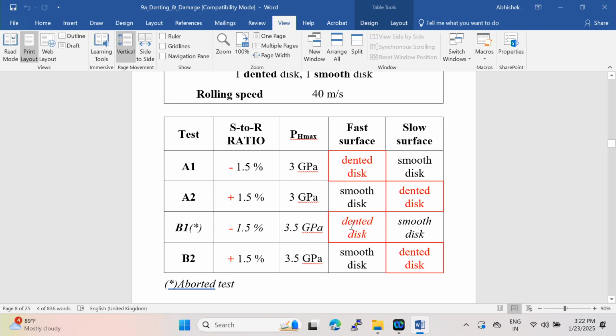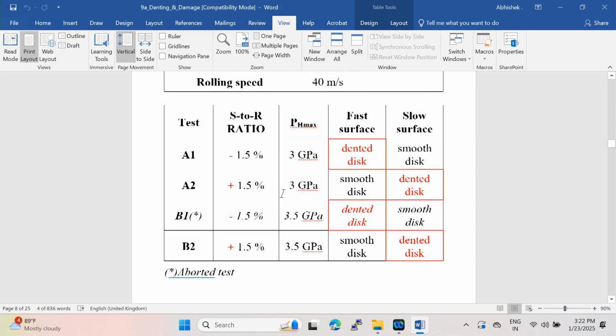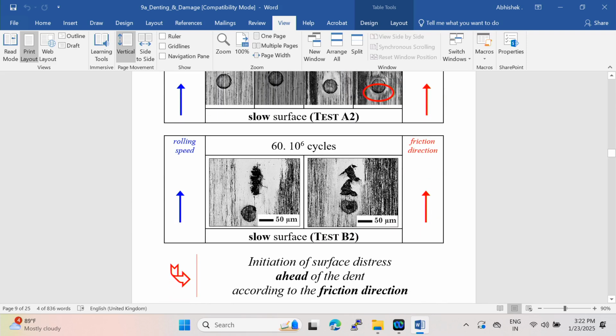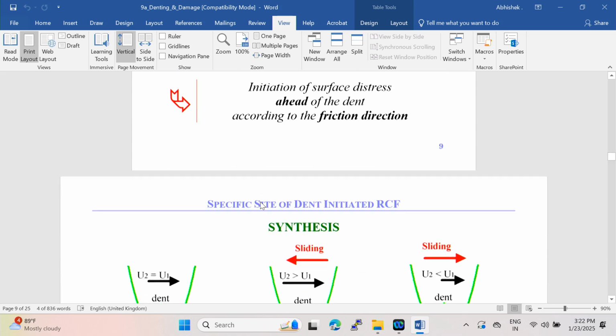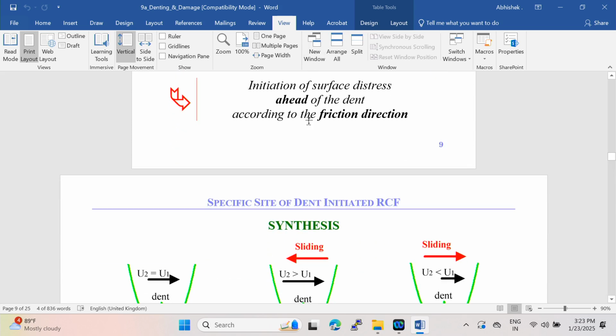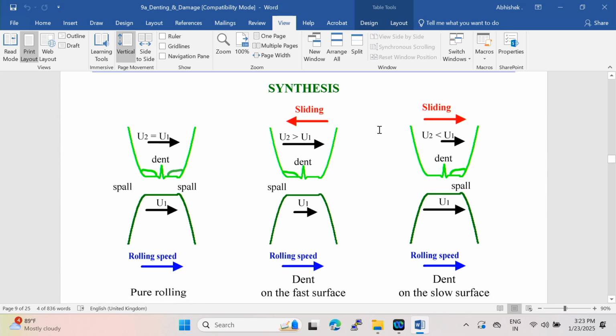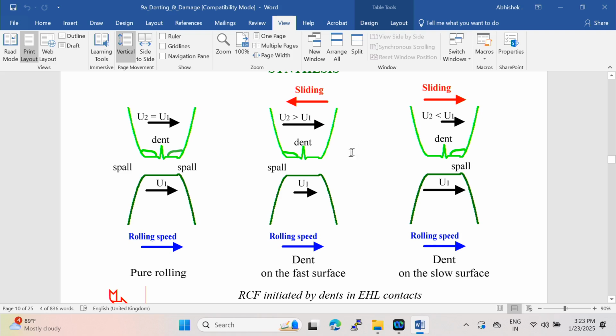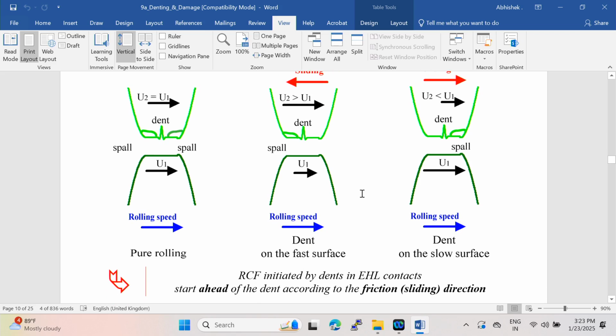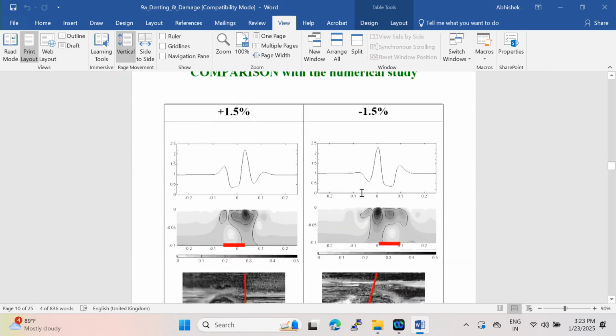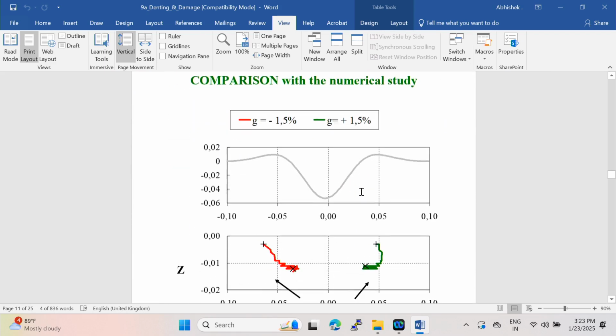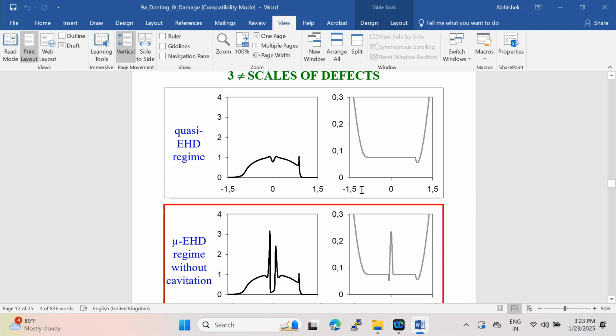And if the dent is located on the fast or on the slow surface, then there is always some slide-to-roll ratio, and you can see here how the damage can propagate nearby the dent, then propagate ahead of the dent according to the friction direction. I would like mostly to emphasize something which is due to the sliding. Then, okay, this is the location of the spall. It can be ahead or back to the dent. Okay, maybe not this one. Okay, we can skip this one.